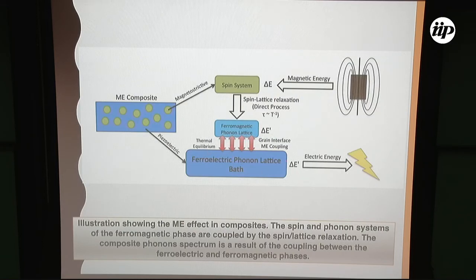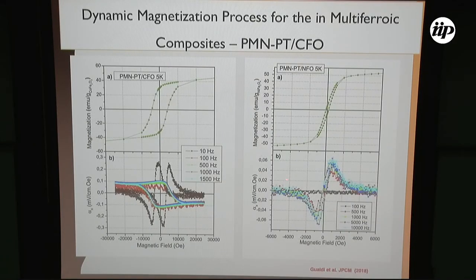because there is 18% of piezoelectric material in comparison with 20% of ferromagnetic material. This coupling produces electric energy through the change of the size of the grain, which makes a pressure on the ferroelectric environment and produces, via the piezoelectric effect, a current in the sample. However, an interesting result is that the PMN-PT cobalt ferrite shows a clear dynamic.